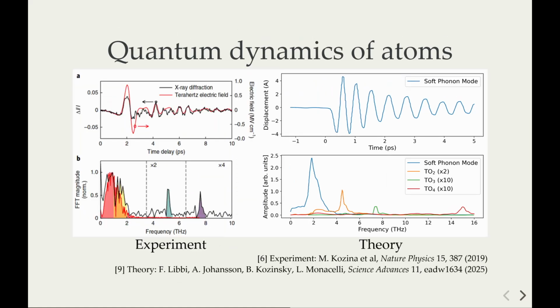This was also observed experimentally: by pumping in resonance with just this mode, they saw higher energy modes appearing in the X-ray diffraction spectrum. This means energy is actually transferred from low energy to high energy, which is very counterintuitive. Usually you'd expect high energy modes to decay into low energy ones, but here it's the opposite—you pump so much that the energy goes up in frequency.